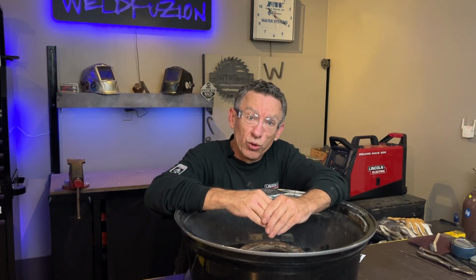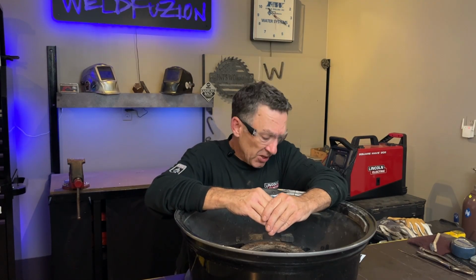That's why most manufacturers only recommend you preheat to about 250 degrees, 300 degrees maximum if you really know what you're doing. But at that point, it's really easy to overheat it and get into that annealing or overaging condition, which can weaken the aluminum. So again, what we're trying to do is burn out the grease and the moisture. And if we get just a little over 200 degrees Fahrenheit or 100 degrees Celsius, we're going to accomplish that goal. So there's no reason to get it any hotter than that. Right on? Now let's look at some ways to preheat.